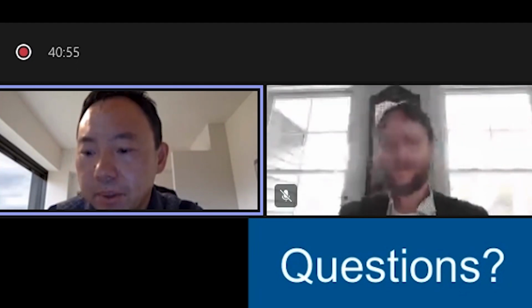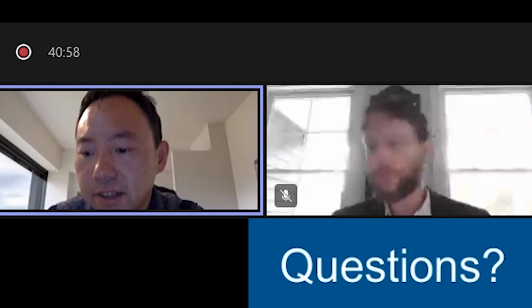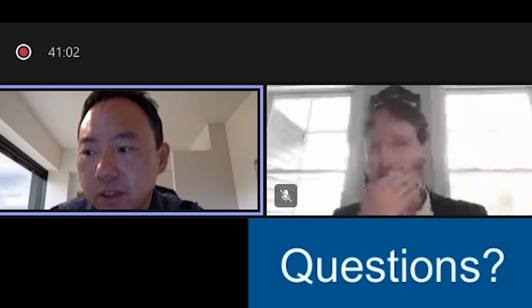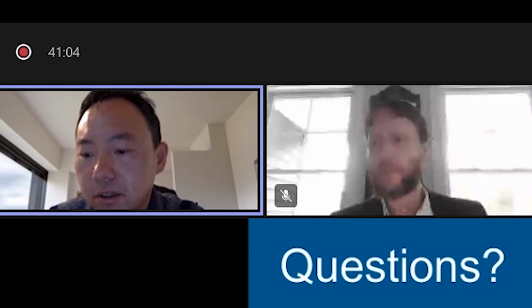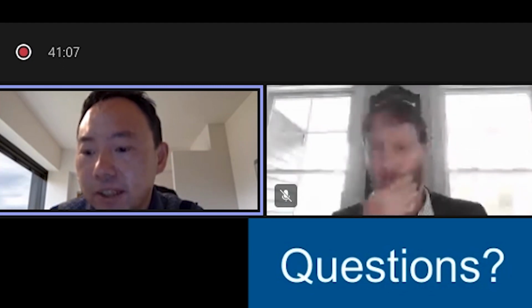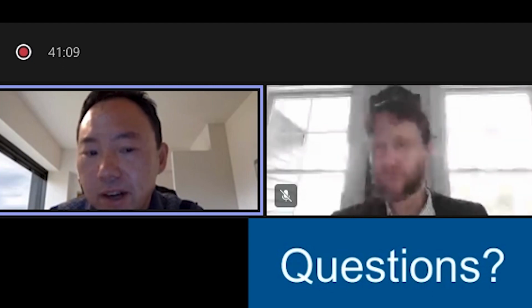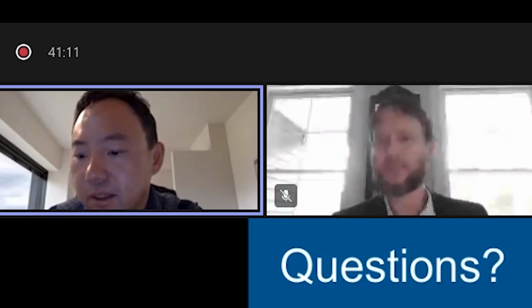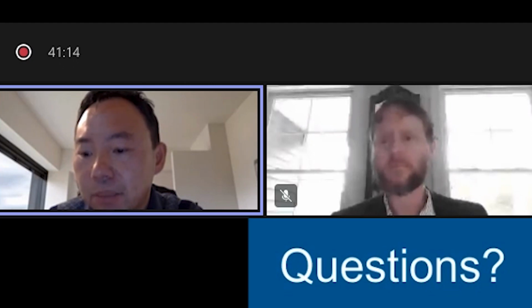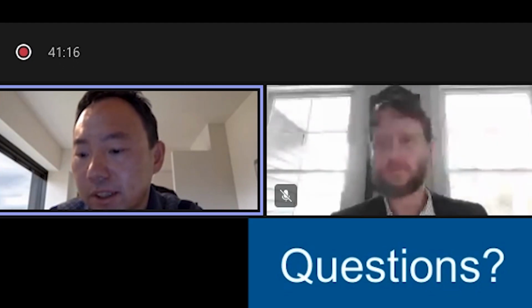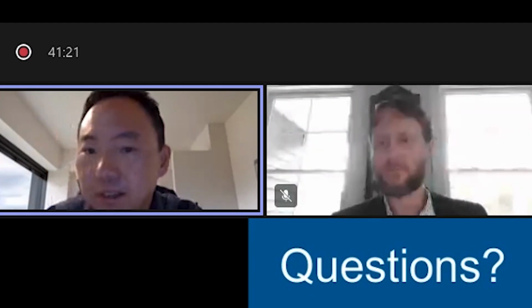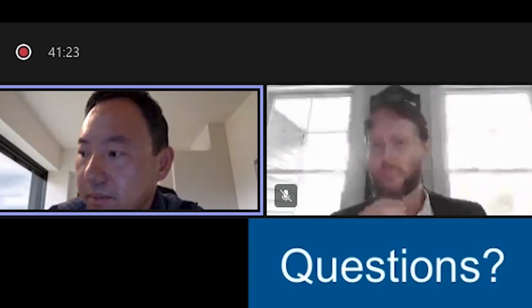Okay. Yeah. So I think David's calculation of mixing energy between the actinides and the salts is important data that can be used in CALPHAD modeling to give this kind of solubility data. I think ab initio MD will not directly tell you the solubility, but the mixing energies it provides can be used for CALPHAD modeling. That will give the solubilities. So if David can add something, that will be good.